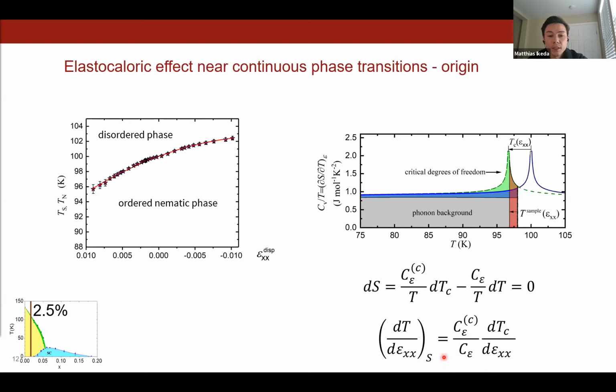And this is a really exciting result because it tells us that the elastocaloric effect measures the critical contribution of the heat capacity without actually having to measure it against a very large background stemming from non-critical degrees of freedom. And I would like to mention here as well that it is through our AC elastocaloric effect technique fairly easy to tune the system into an adiabatic state, because we apply strain in an oscillating fashion, and we can choose the strain frequency such that we arrive in a regime that doesn't allow heat to flow in and